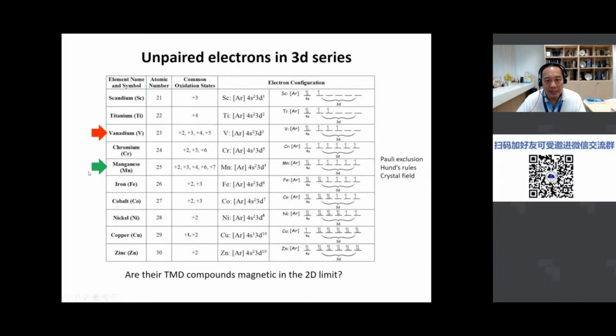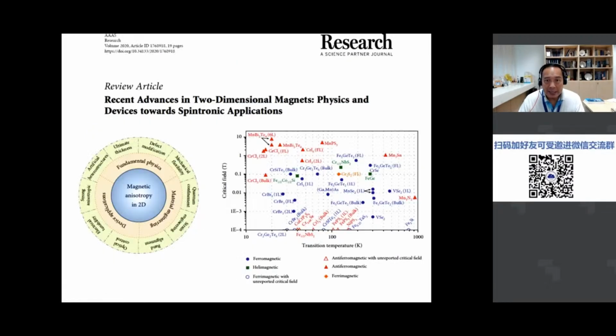The manganese diselenide and the vanadium diselenide. So this is the study on the manganese. Oh, sorry. This is another review paper that summarizes and plots the Curie temperature of all these 2D materials. That's room temperature, 300 K. And as you can see, why we're interested in manganese diselenide and vanadium diselenide is that their transition temperature or Curie temperature is above room temperature. Hence, they have the potential to be used for devices, right, at above room temperature if they are magnetic.